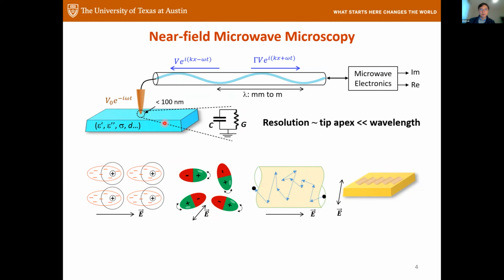And so this is a 2020 work. Actually, we published another one in Nature Electronics this year. Actually 2022 is already last year, and it went all the way down to like 2 or 3 nanometers. And this result shows the dielectric loss. The material is called yttrium manganese oxide, and it's a ferroelectric material. And as you can see in the loss channel, you see the domain walls.